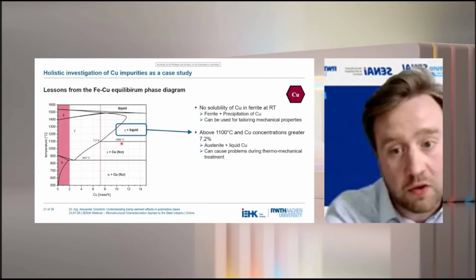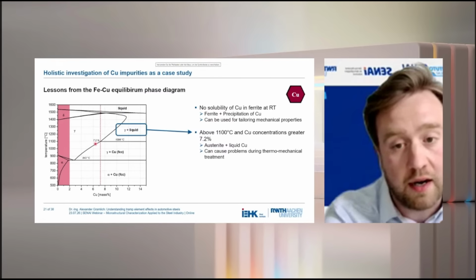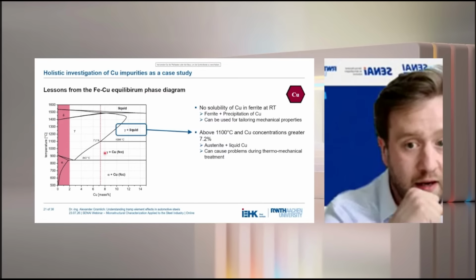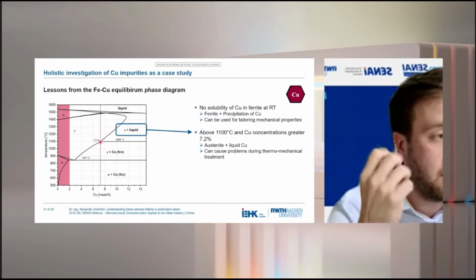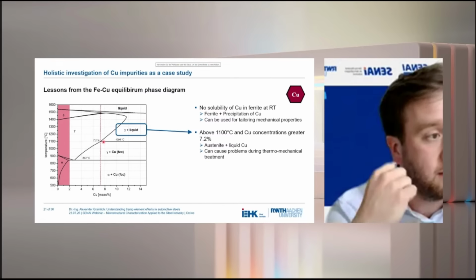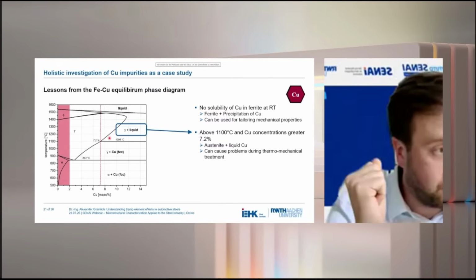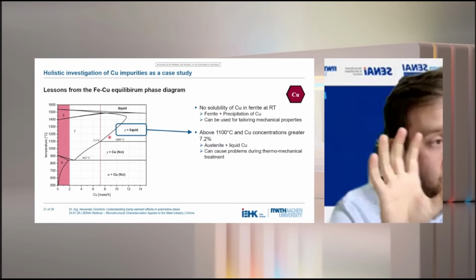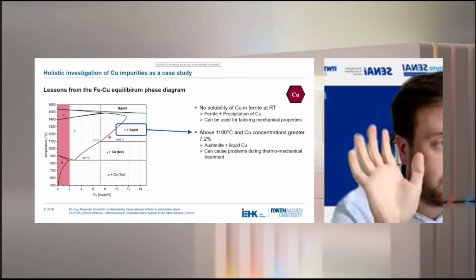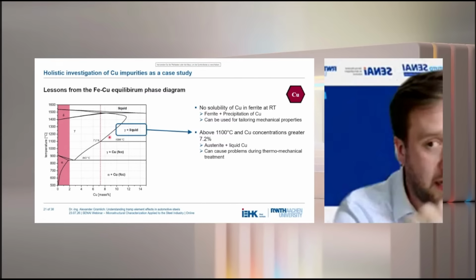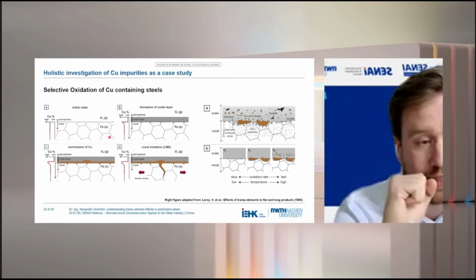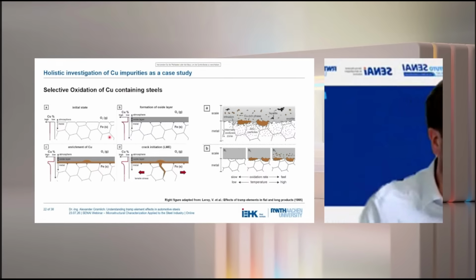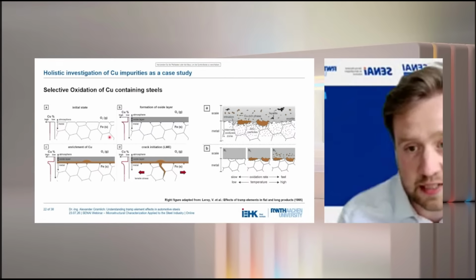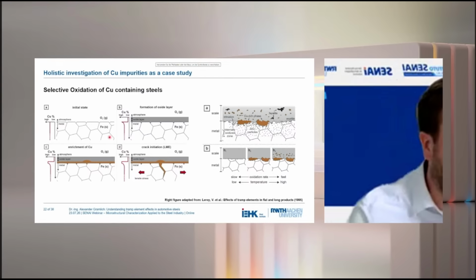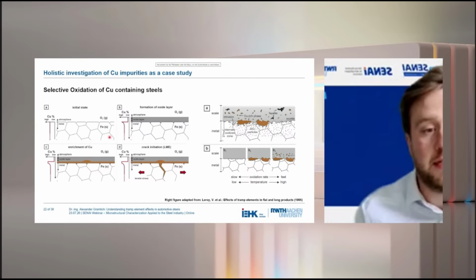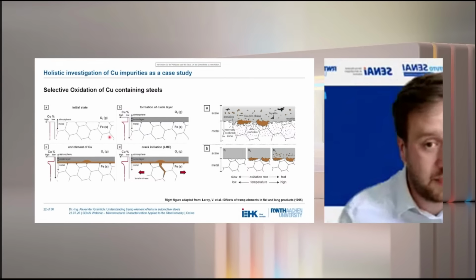However, you might also ask, okay, this happens only if you are above 7.2%. Why is this an issue? So how high will the copper concentrate in the steel scrap? This is true on the one hand. However, this is not a single problem of dissolved copper in the matrix. The reason for this is that the copper-induced hot shortness, so the hot fracture of steel slabs, is a combined process of liquid metal embrittlement and selective oxidation.